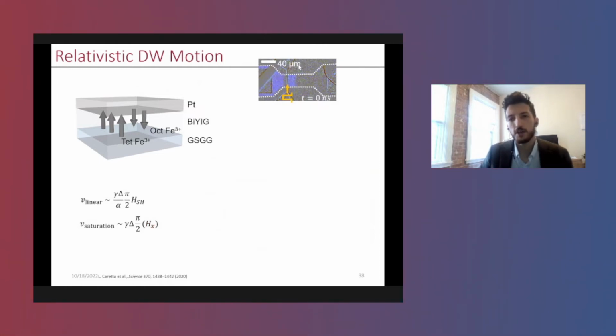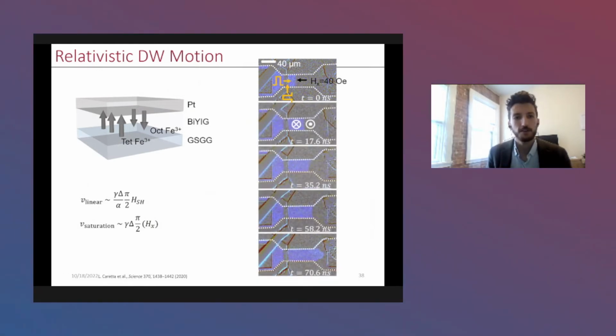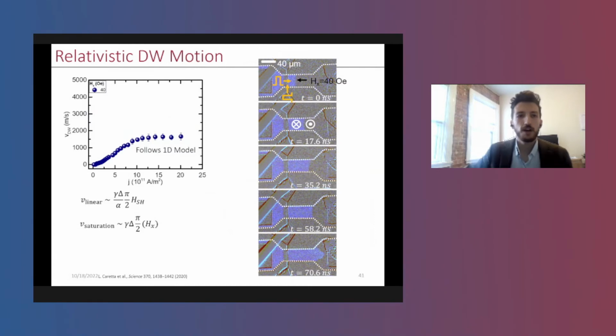We can nucleate domain walls in racetracks, apply fields to stabilize Néel domain walls, and currents to drive these domain walls into motion. And what you find, on the left here, is a plot of velocity as a function of current density. And you'll see that these domain walls follow a similar 1D model. We have a linear regime and a saturation regime, where now the saturation does not depend on the strength of the DMI. It actually depends on the strength of the in-plane field you apply. So the larger the in-plane field, the stiffer the domain wall, the more it resists its deformation towards a Bloch configuration. And this is proven experimentally.